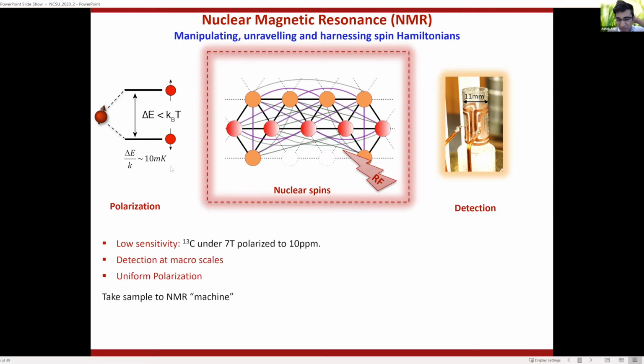And this population imbalance can be extremely small, right? So even at a large magnetic field like 7 Tesla, carbon-13, which is a very popular nucleus, has only a population difference, or what's called polarization, of about 10 parts per million. So it's a very weak signal.